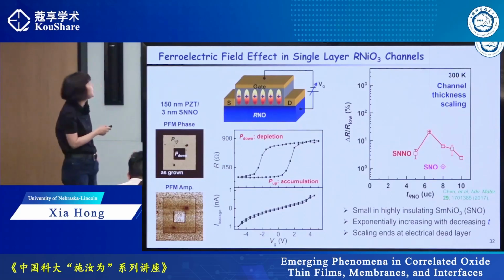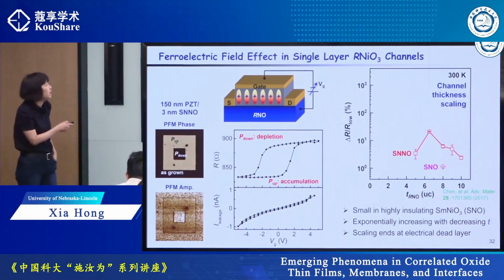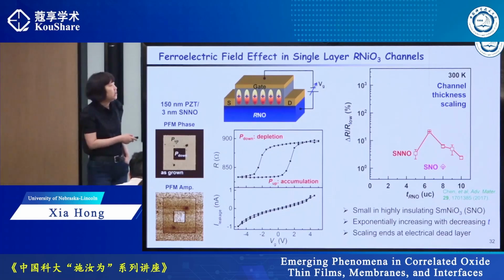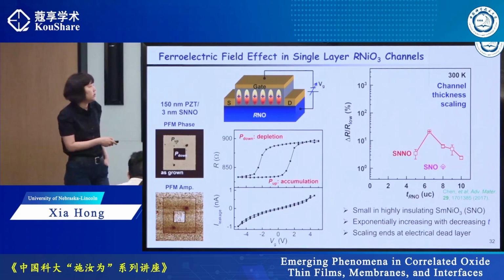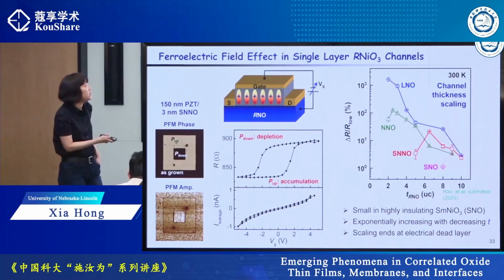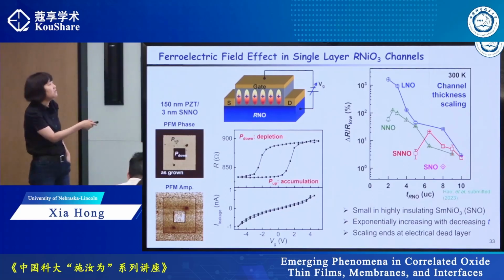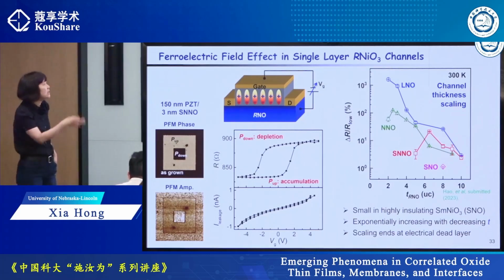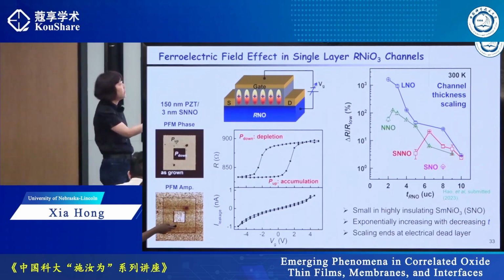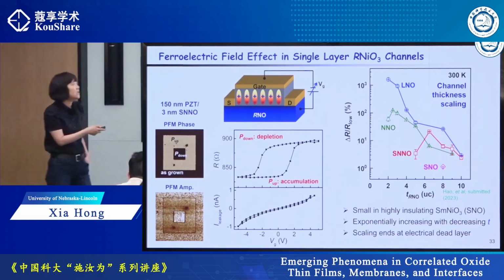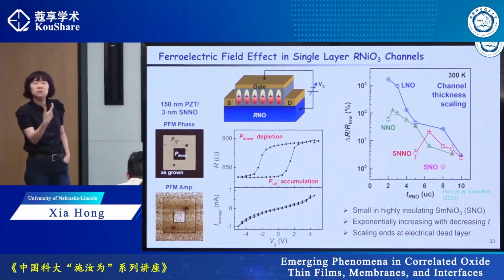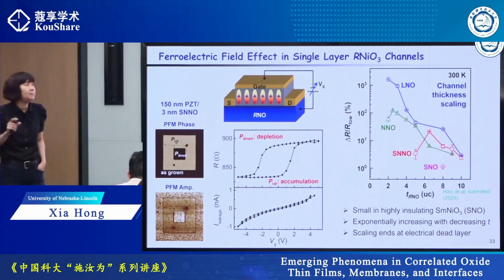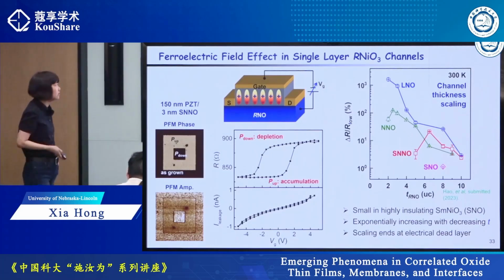We have ferroelectric-gated rare earth nickelate channels, and we systematically tune the thickness. You can see that in the metallic phase, they follow more or less the same scaling behavior. The more you can reduce the channel thickness without touching the ferroelectric layer thickness, the higher the ratio you can achieve, and the highest one is on par with what has been reported previously. So it seems like an intrinsic limit that you cannot really overcome.